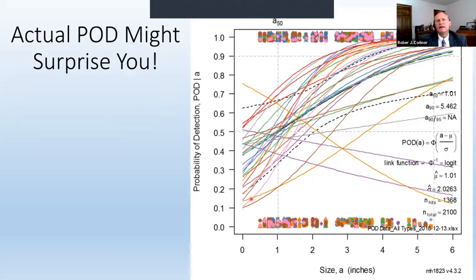And so when we look at the data, the 50-50 crack, 50% probability of finding or missing, is about an inch. And 90% probability is about 5.5 inches long. So, you know, 25 millimeters, that's a pretty good size crack. Now, remember, I said there's no guarantee that the structure can tolerate that crack. That's just where we are in terms of detection. Now, we're going to come back to these numbers in a little bit.